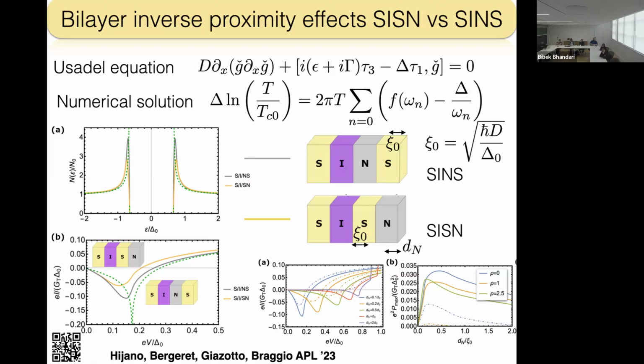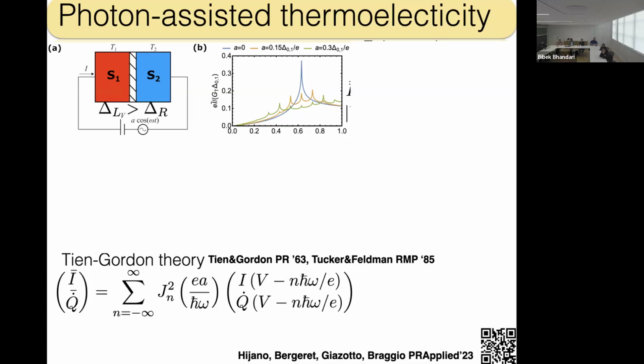bipolar thermoelectric effect. I want to show you another possible application because it's inspiring to me, and I'm actually working on this type of problem for a different reason. Essentially, you have this bipolar thermoelectric effect, and you shine an AC drive on it. And you can do photon-assisted tunneling. In this photon-assisted tunneling, you see that the single peak of the bipolar thermoelectric effect becomes split. This is the dissipative part, but the matching peak will be shifted by the sideband. Essentially, this is what you expect for photon-assisted tunneling. And you ask, does it work also with thermoelectricity? Yes.